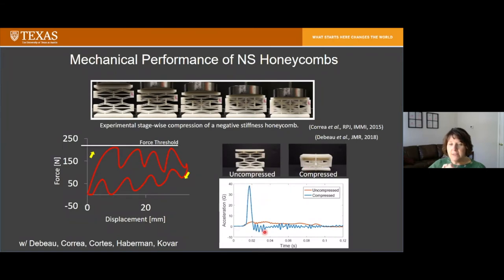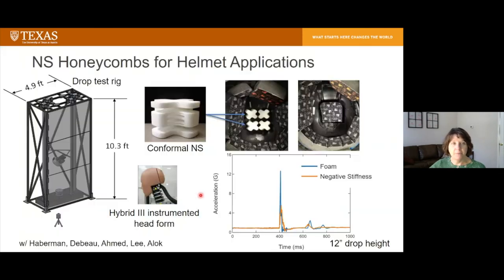And here you can see the difference in acceleration, or G levels, experienced by that mass as it lands on the compressed honeycomb in blue and the uncompressed honeycomb in red. So it's taken what would have been a 40G impact and reduced it by an order of magnitude. And so this is indicative of many of the things that we see from this particular honeycomb.